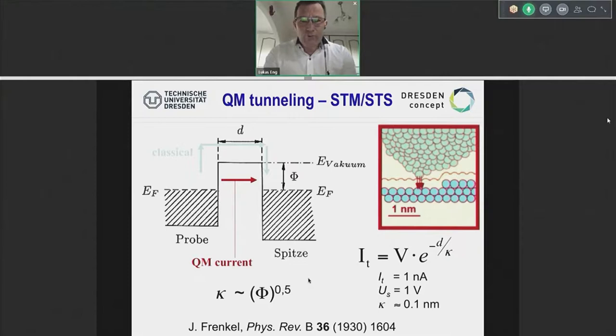Tunneling is the one and, I would say at the moment, still the best resolution method of these scanning probes. In STM, what we are using is a tunneling barrier, as you can see, between two materials called Probespitze in German, or sample and tip in English. And the goal is to drive a current across the barrier. This current typically is on the order of about 1 nanoamp. And if you look at the cartoon here, it depends on a couple of things, like the distance between these two things, which is the d here. And it depends also on this kappa, where we have inclusion of the work function difference phi. You can see that basically here in the cartoon.